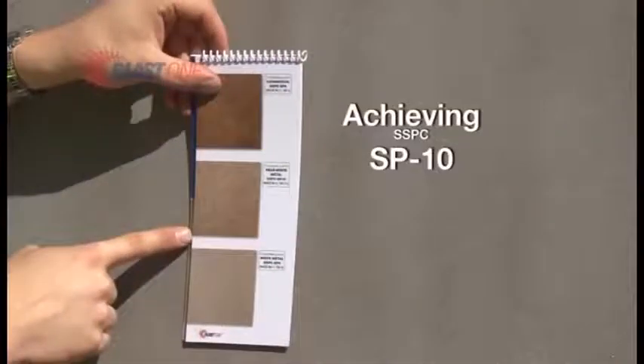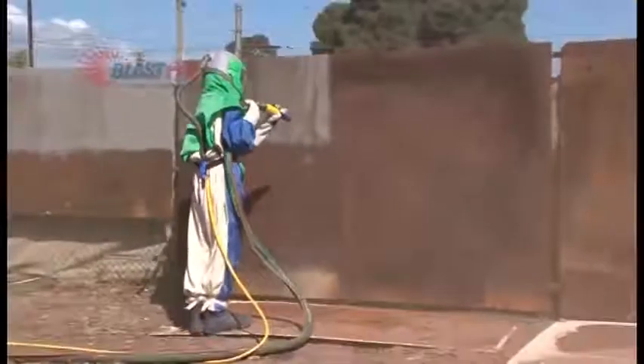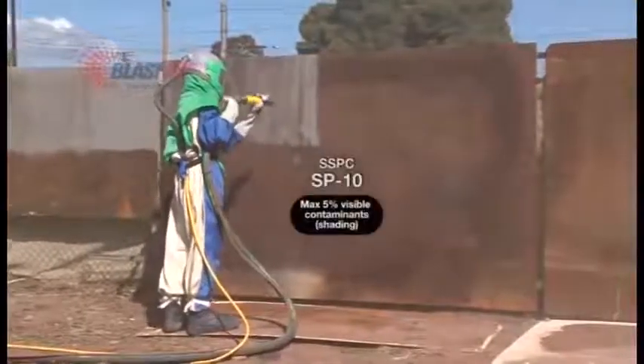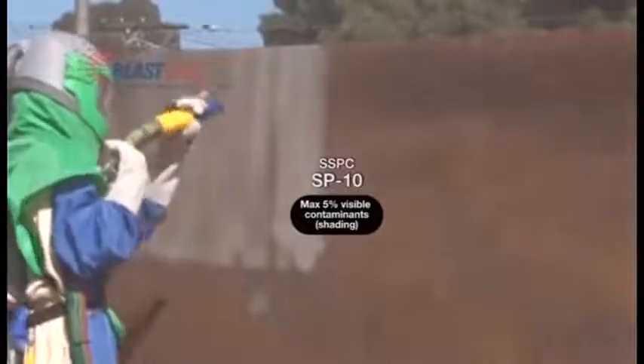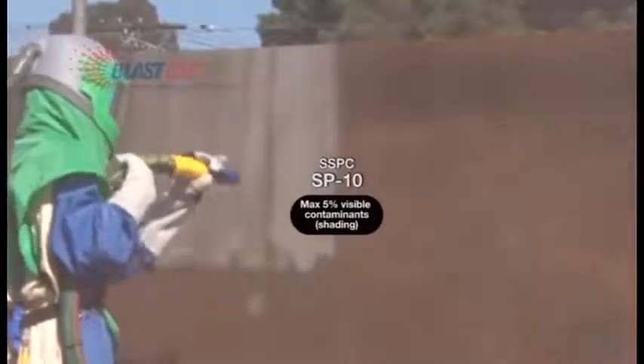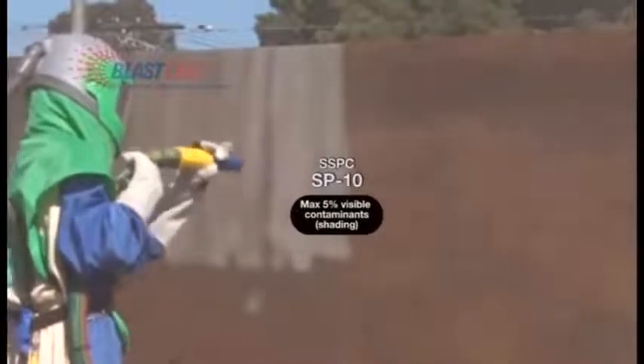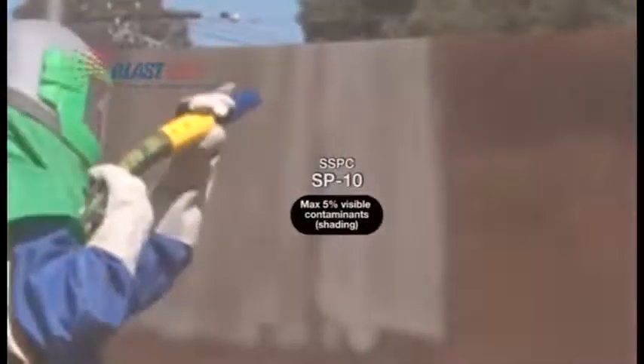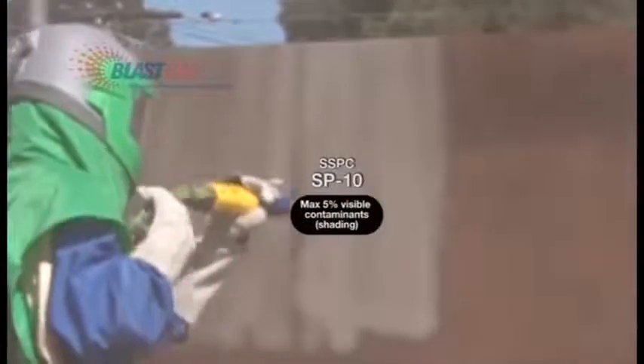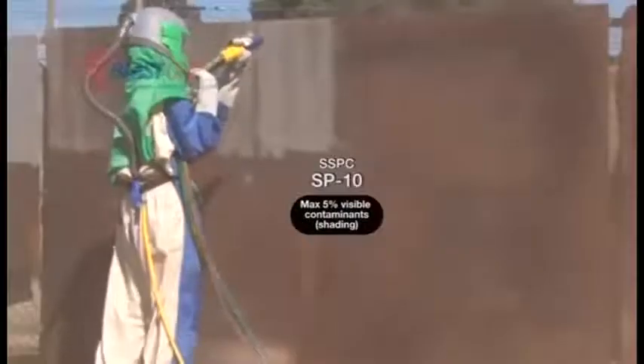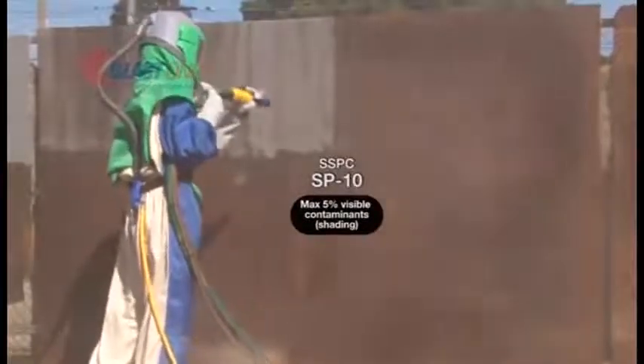How to achieve an SSPC SP10. The specification for SP10 requires a resulting shaded gray metal with only tiny isolated strips of visible contaminants. The blasted surface would have a maximum 5% visible shading. With denser corrosion on a grade C substrate, to achieve SP10 with shading less than 5%, the blaster must move much more slowly than he did on grades A or B. As you will notice, he is methodically aiming his blast pattern, overlapping it to ensure that the shading is smooth and consistent throughout.